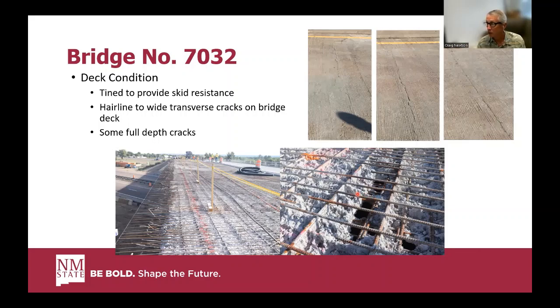That surface was to be tined, and then that surface was to be prepped, and the UHPC overlay was to be placed on top of that HPD layer. And the HPD is just high performance deck concrete. So actually kind of a 2-layer overlay system from the existing concrete. There was also some work to extend the deck horizontally, laterally, which really doesn't play into the project as we performed it.